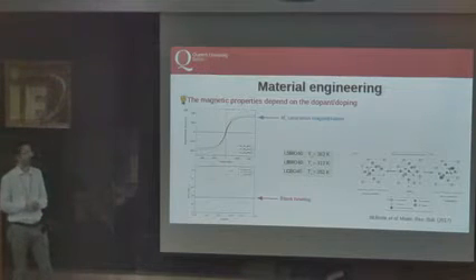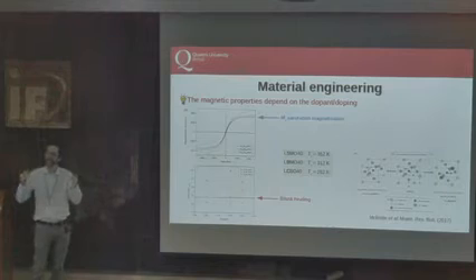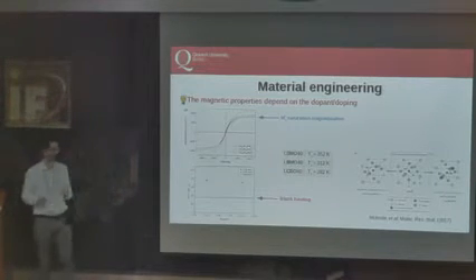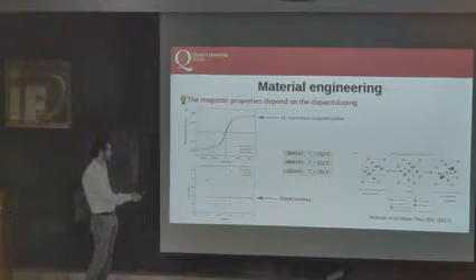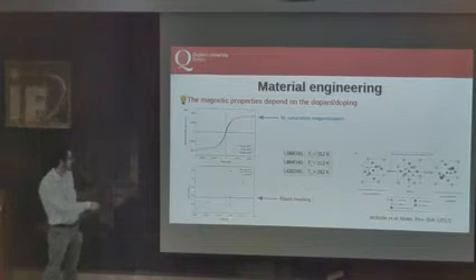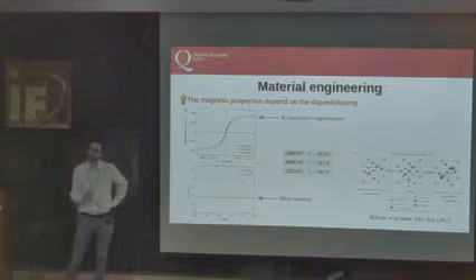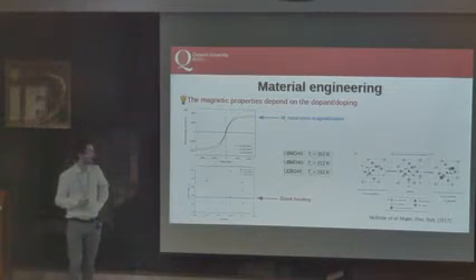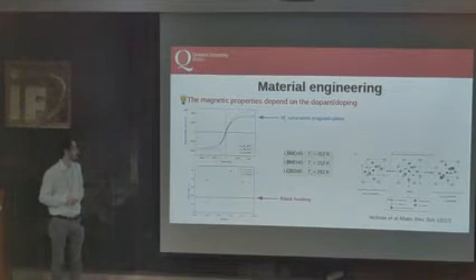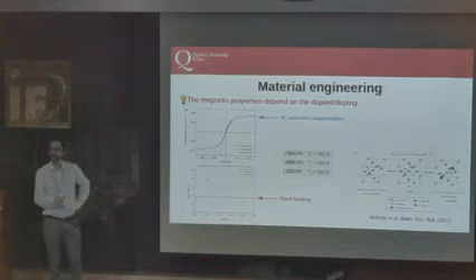We measure this, of course, before every experiment, so let me say a positive heating is above the blank, a negative heating, if we can say this, is below the blank. And again, this is a small figure, unfortunately, but you can see the lanthanum strontium manganese oxide for different levels of doping is always above the other compounds. And the doping with 0.35 amount of strontium seems to achieve the highest SAR. We wanted to understand a little bit better why, or what is peculiar in this compound, so the rest of this talk is mostly focused on this LSMO 35, which stands for 0.35 doping of strontium.